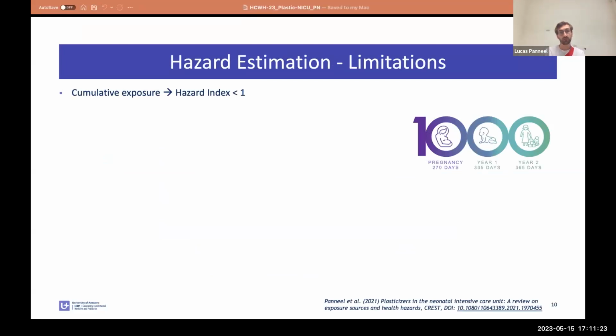And one approach is to sum the estimated intakes and compare them to one reference dose. And so you can calculate a hazard index, which was still below 1. In this study, this was about 0.35, which suggests that the current exposure is below the reference levels.